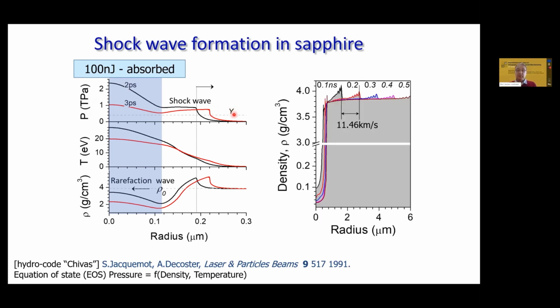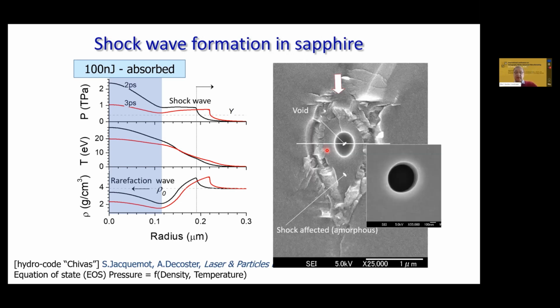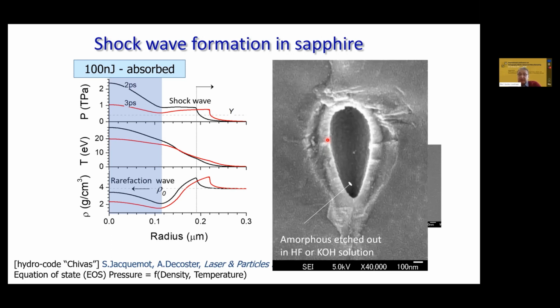If you look at simulations for longer times, you can see an opening depression in density. This is the void which we saw, and you have a shock wave with a small amplitude passing out of the focal region of modification. The radius of this opening is actually twice larger than we saw in experiments, but we consider it good enough as a first description. You see the void in the center, and around it amorphous material, which has a density larger by the volume you expelled from the center. It is not very usual to have an amorphous state which is more dense.